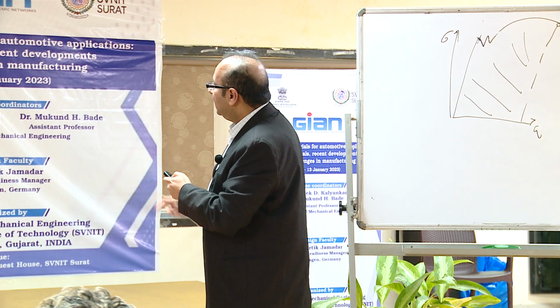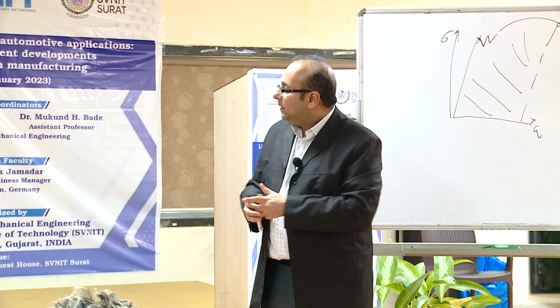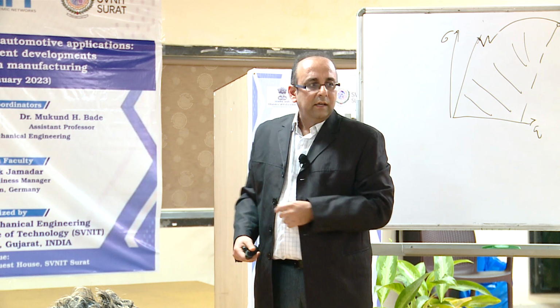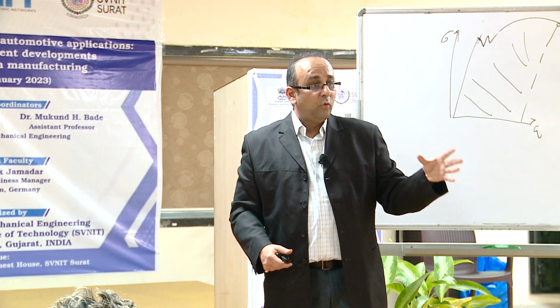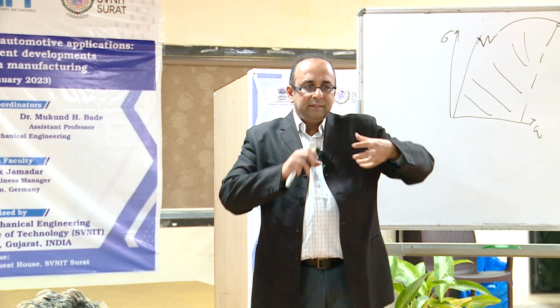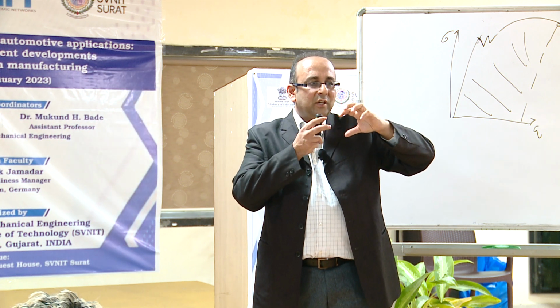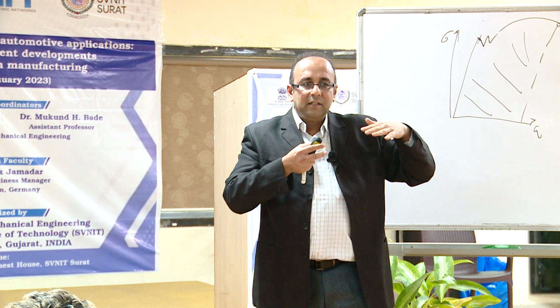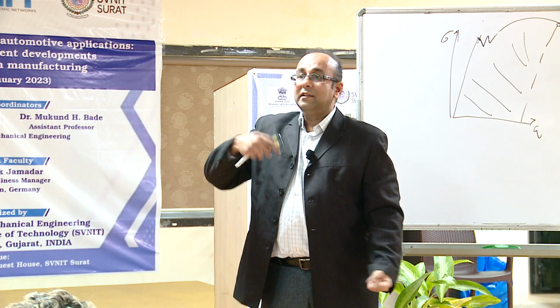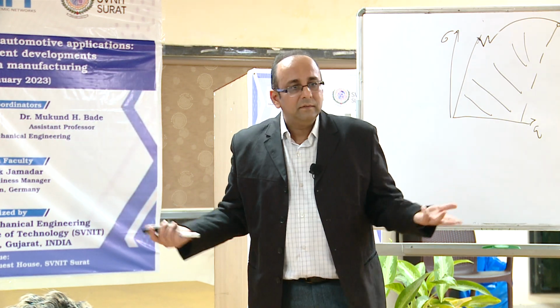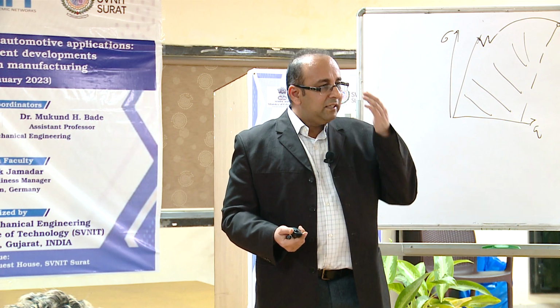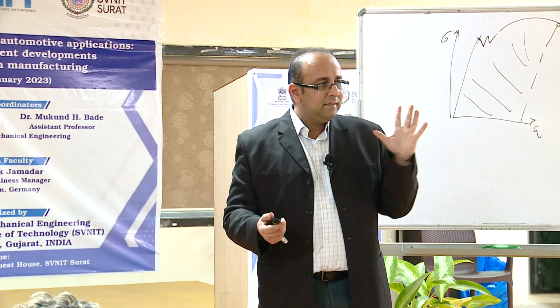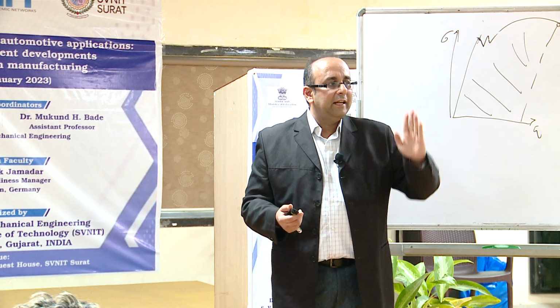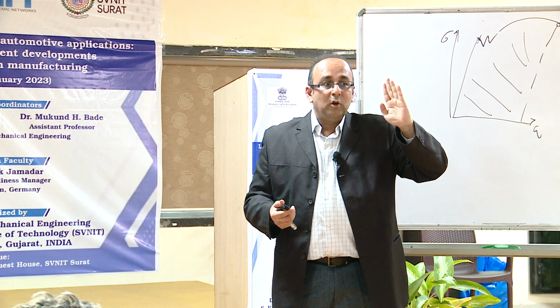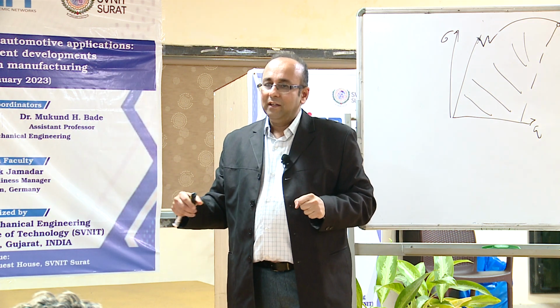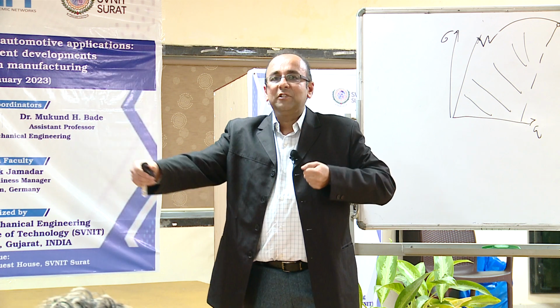Now people tell, okay, what is high alloy steel then? You know that this structure, this is pure iron. Let's remove one iron and put chromium or vanadium, molybdenum. Automatically you realize that structure is getting damaged. Structure is getting deformed. The slip cannot happen so easily. It means the strength increases. This we call a high strength steel. So basically you see the logic is very simple. You have to create resistance to the deformation. You automatically create the high strength. But at the same time, your resistance should not be such that it can create cracks. Otherwise the purpose is not solved. It should go much and much endlessly.